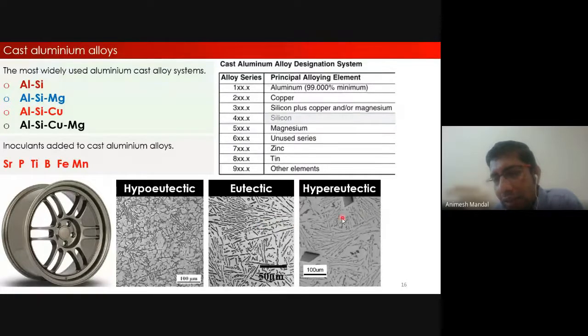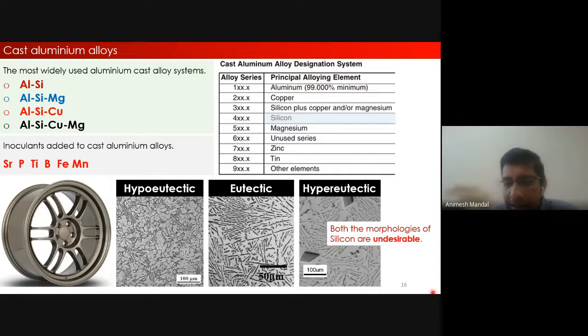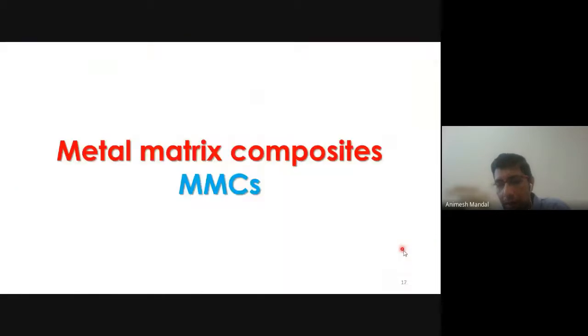In hypereutectic, in addition to the needle shape silicon, you also have primary silicon, which is quite coarse. Both of these morphologies, the needle shape as well as the polygonal primary silicon, generally you do not desire in this kind of alloys. So how to modify this morphology? You can modify the morphology of the needle shaped silicon as well as the polygonal silicon using elements like strontium and phosphorus in different amounts. This is something you need to understand. A very, very trace amount, of the order of a few ppm, is good enough to change the morphology of this particular alloy.